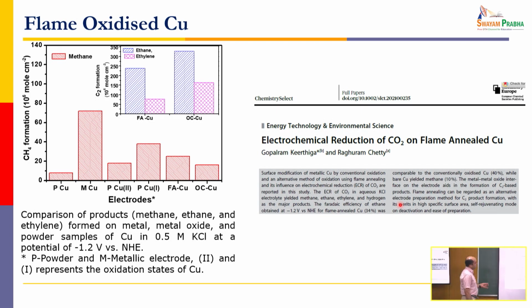Usually people take some copper foil and put it in an oven and leave it for some 8 to 10 hours at a particular temperature, and they convert copper into copper oxide, and then use that as an electrode material. So that's something people do. What we did is, we took a copper foil and used a Bunsen burner, put a flame, and you just keep that electrode for 2 minutes and convert it into oxide, and then you can use that as an electrode or a catalyst. So in that way we tried.